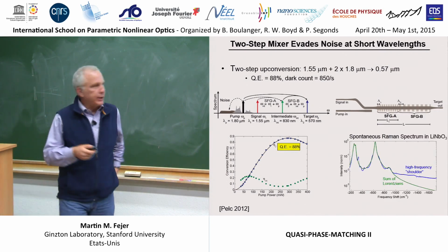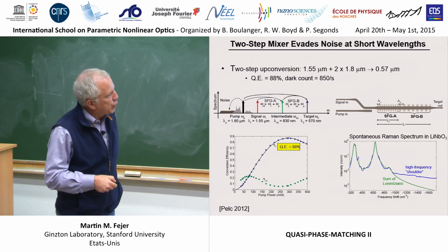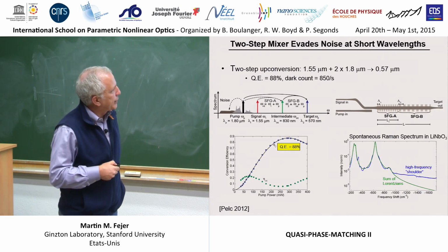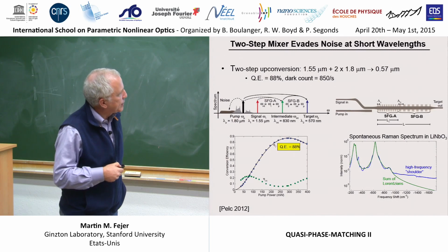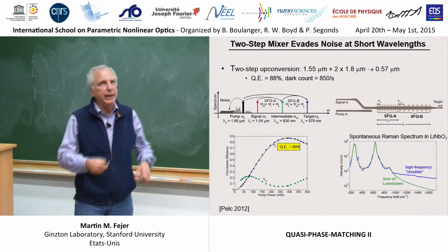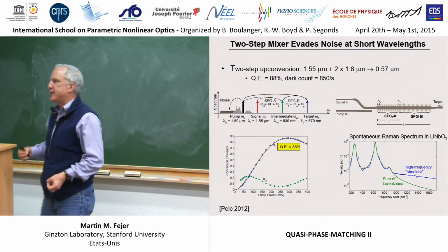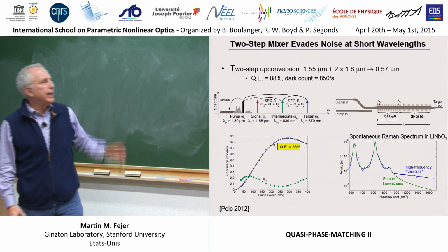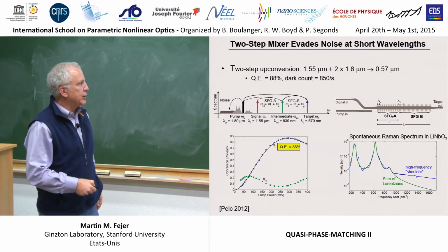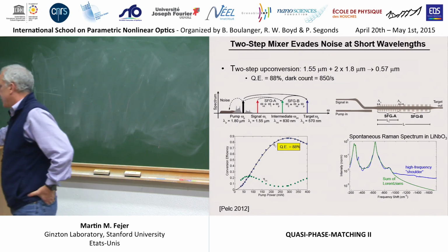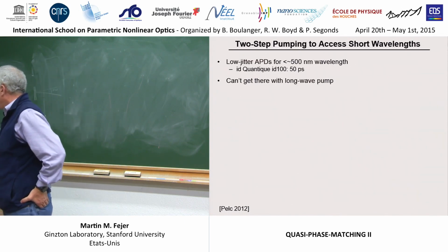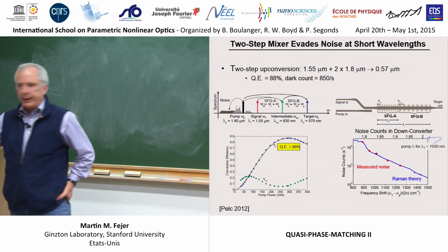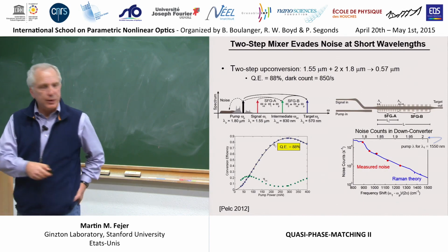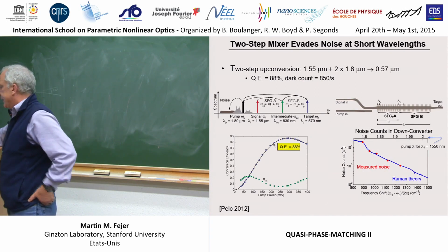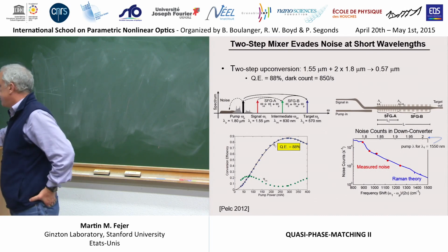It turns out they are dominated by this goofy shoulder on the Raman cross-section, making the anti-Stokes a bit worse than you would expect. But still, if you're at a few hundred dark counts a second instead of a few 100,000, you've now put this thing in a regime where it's actually useful for doing quantum optics. And you could exactly explain the excess noise now by the spontaneous Raman scattering rather than by this disorder phase matching.